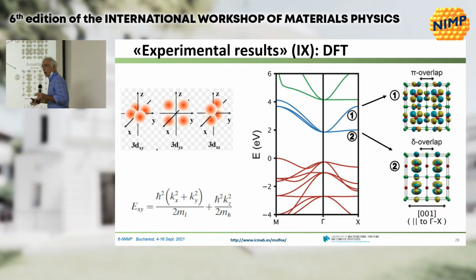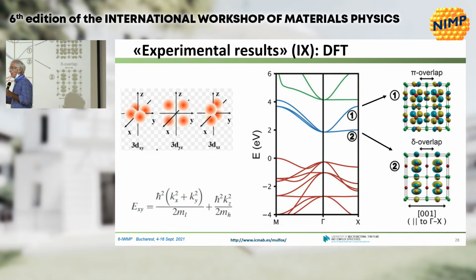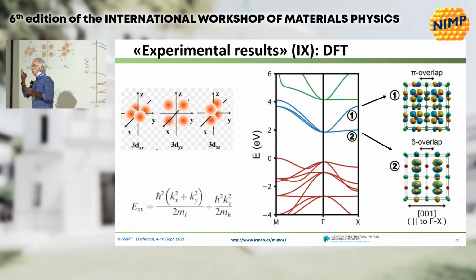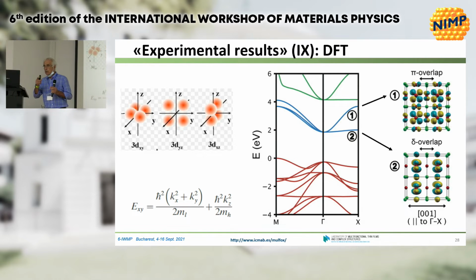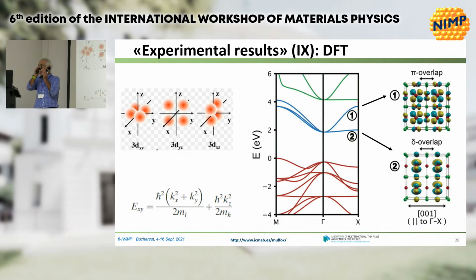Final comment. I mentioned that in these vanadates, we have one electron in a degenerate t2g band where six states are available. It's obviously a metal. If that were a spherical Fermi surface, I would not get any magnetoresistance, but magnetoresistance is there. So I cannot escape from the data. But if I pay a bit of attention to the electronic structure of strontium vanadate, it's obvious that the Fermi surface is not a sphere.